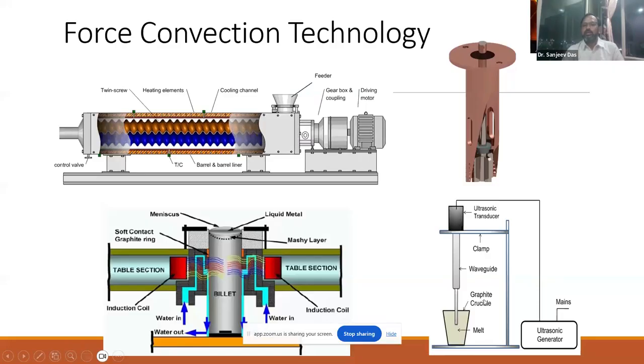The fourth one is basically your ultrasonic way of creating the forced convection. There is a process called cavitation. When you pass ultrasonic sound, there will be formation of very small voids. Then these voids will capture a lot of dissolved air inside. The bubbles increase, the pressure inside goes down, and there will be a collapse. And when it collapses or implodes, there will be a lot of agitation inside the metal, and by that agitation you can create convection inside the liquid metal.